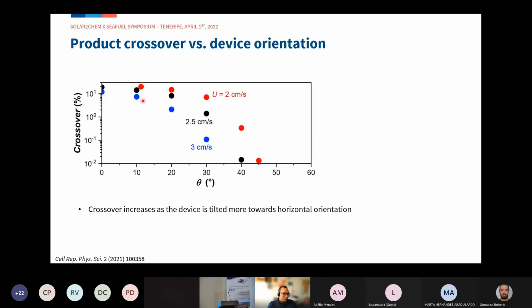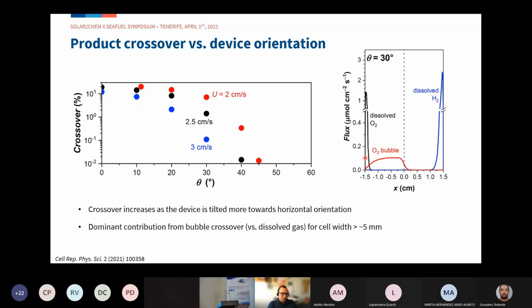If we look at what contributes to this crossover, we can distinguish it into dissolved oxygen and oxygen bubble, or either dissolved oxygen or hydrogen. But here we see that if you have the cell width larger than 5 millimeters, you can actually minimize the crossover due to dissolved gases, and only gas bubbles contribute to the crossover.